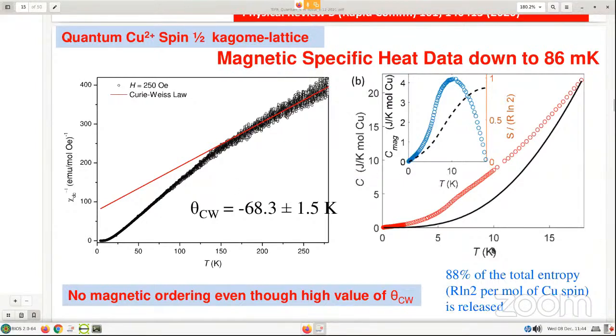In fact, the specific heat as a function of temperature, by the way, this specific heat down to 86 millikelvin was carried out in collaboration with Professor Dhar, and we used the TIFR facility. So for the specific heat down to 86 millikelvin, what you see is that though 88% entropy is released down to 86 millikelvin, there is no magnetic ordering. Now the question is, only 12% entropy is remaining if it has to undergo any magnetic ordering below 86 millikelvin, which is very unusual. So this is for the non-magnetic counterpart zinc, and this is the net magnetic, and this is the entropy calculation.